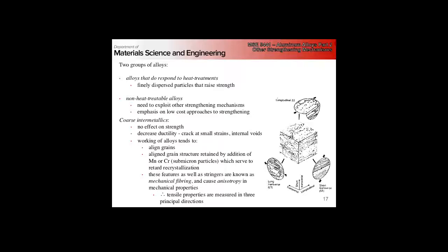Remember our working of the material. We tend to align the grains and get these stringer formations, and that gives us a strong anisotropy in the mechanical properties. So that means whenever we report the properties of a cold worked alloy, we generally have to think about it in three directions. The first one is along the fiber length, the transverse direction, and then the short transverse direction, which is normal.